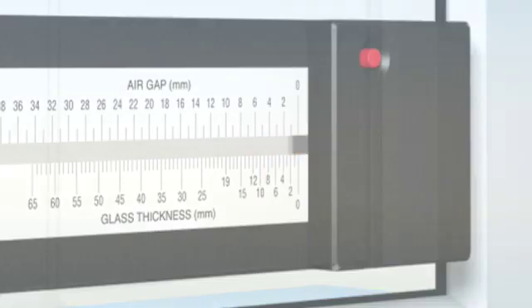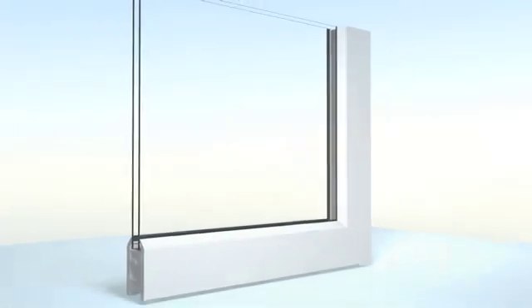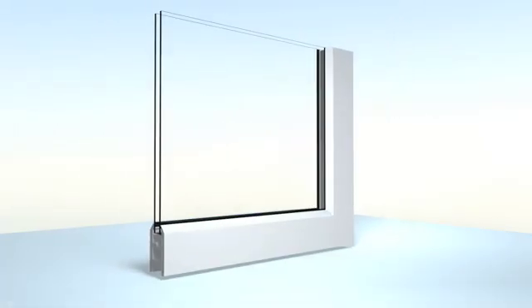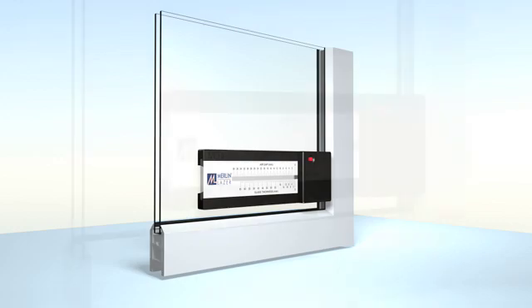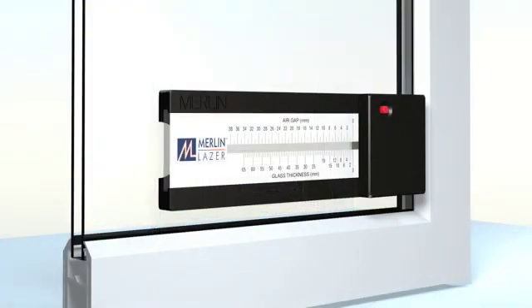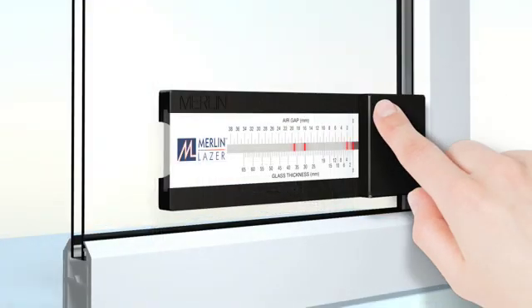One of the most common uses for the Merlin laser gauge is to determine the makeup of double-glazed sealed units. When measuring multi-pane units, ensure that the right hand side of the tool is placed into the bottom right or top right corner of the unit in order to obtain a true reading of the air gap, as air gap thicknesses may deviate towards the centre of the unit. As before, activate the laser and move your head so that the lines become clearly visible.